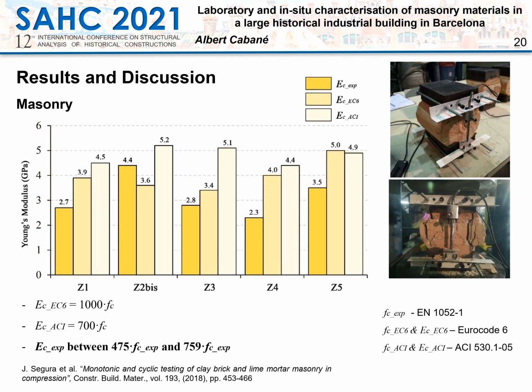The Young's modulus of masonry has also been analyzed in this campaign. The Eurocode suggests a value of 1000 times the compressive strength, while the American requirement suggests 700 times. This graphic shows that the Young's modulus estimated from the standards could be overestimated compared with the experimental ratios, ranging between 475 and 759 times.